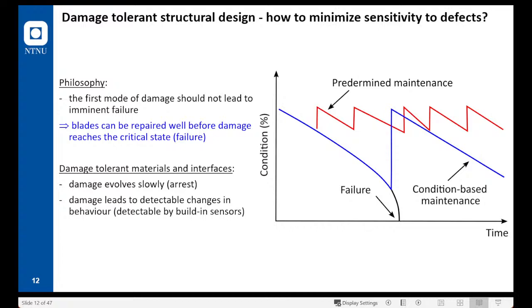By having damage-tolerant materials and structures, we can avoid all these unnecessary inspections, and we can have our blade operate continuously. Now the damage grows, but as I said before, the damage will grow slowly, and also the growth is predictable, and therefore we know when we have to stop the operation and repair the component or the blade. So now the blade becomes almost like an intact blade, and then we continue the operation. In this way, we can reduce a lot the cost of maintenance. Indirectly, we can reduce the cost of manufacturing, and therefore we can reduce the cost of electricity.